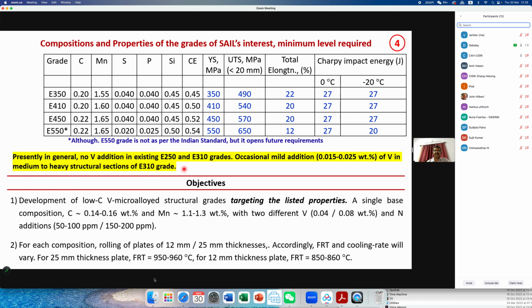Now, Steel Authority hardly uses any vanadium in their existing E250 or E310 grade. Occasionally, a mild addition of vanadium is done in medium to heavy structural sections. So we plan to vary the vanadium level and nitrogen level. We plan to develop continuously rolled two thicknesses, 12 mm on the lower side and 25 mm on the relatively higher side. Accordingly, FRT and cooling rate will vary naturally. We are not imposing any forced cooling; we are relying on rolling followed by natural cooling, which is the easiest way of industrial production.